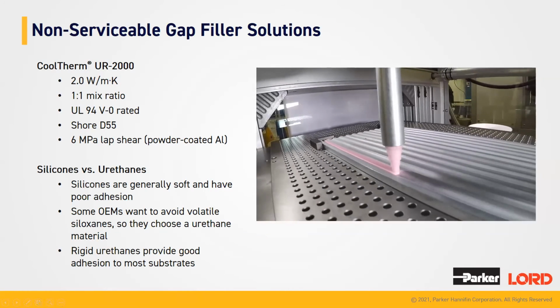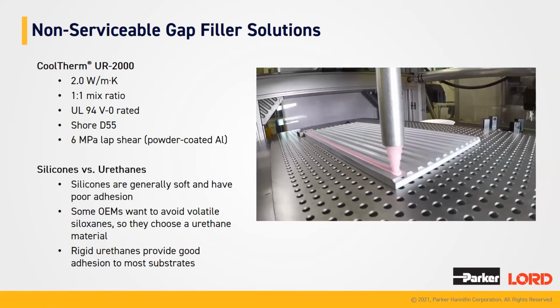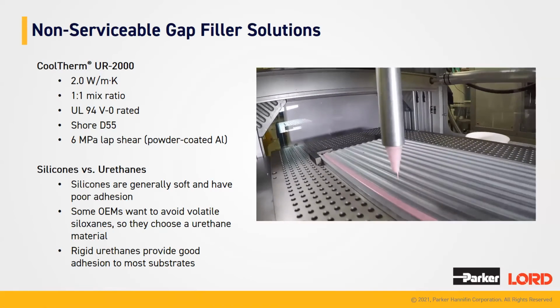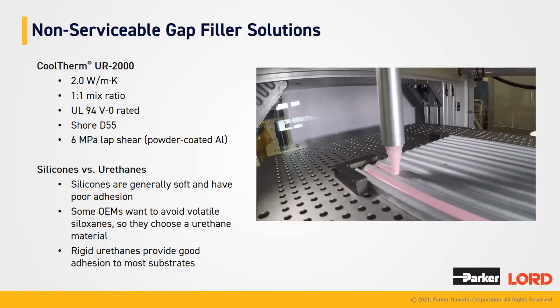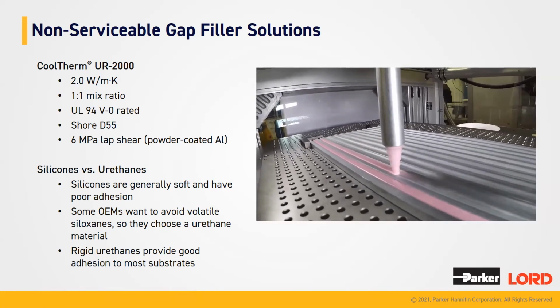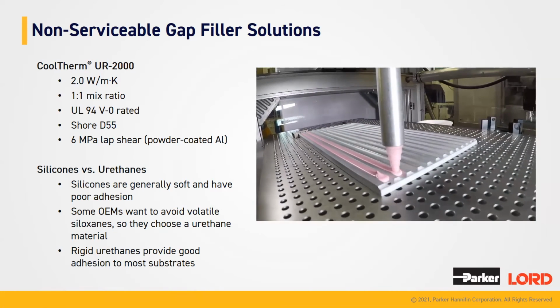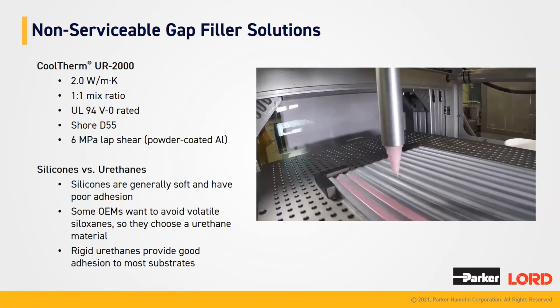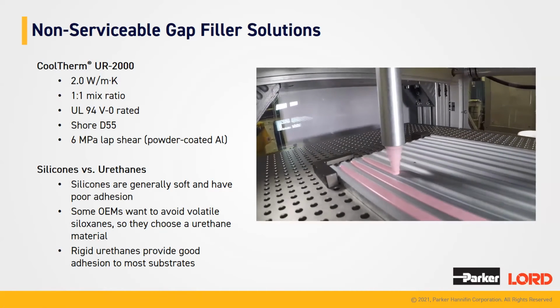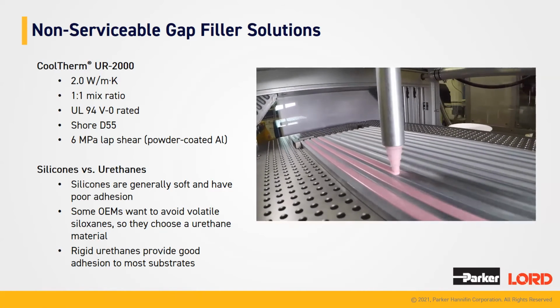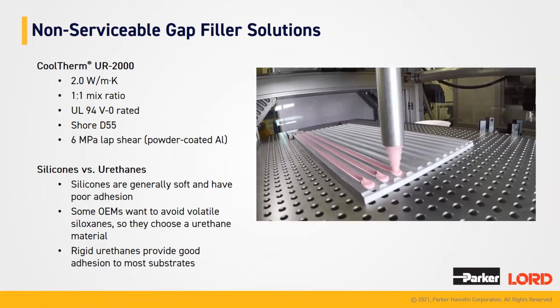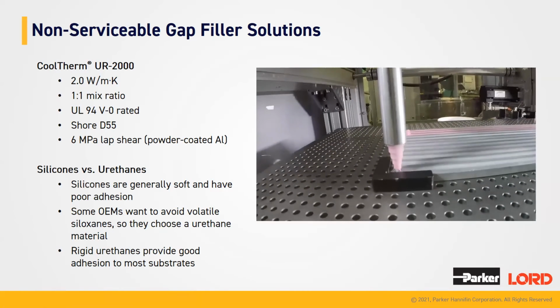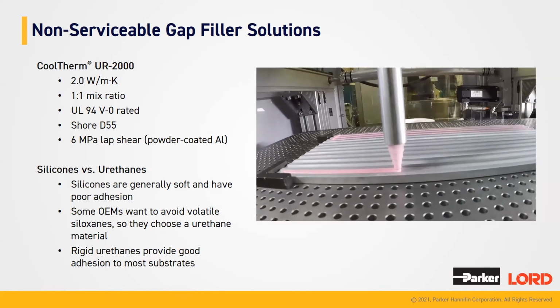So looking at our non-serviceable gap filler solutions, on the right is a video of Cooltherm UR2000 being dispensed from one of our MMD units in our lab in Cary, North Carolina. This is a 2-watt urethane gap filler with a 1:1 mix ratio. It's UL94V0 rated, Shore D55 hardness, and has good adhesion to powder-coated aluminum.